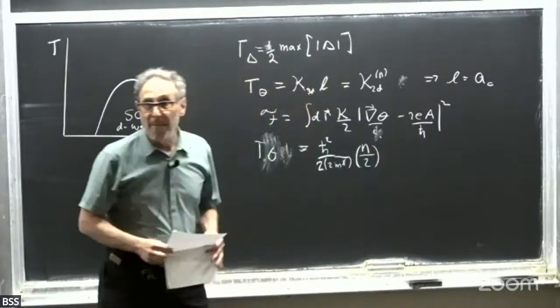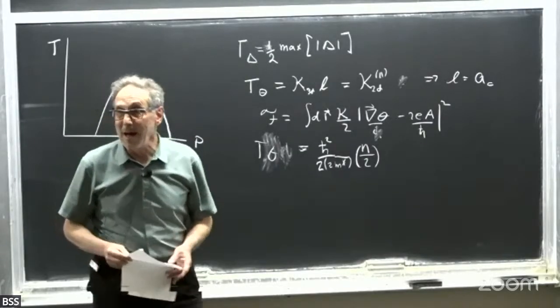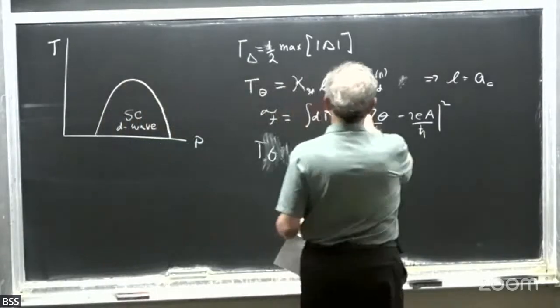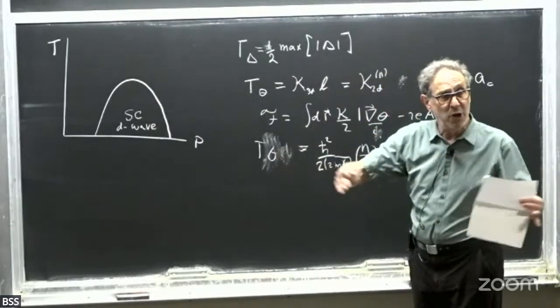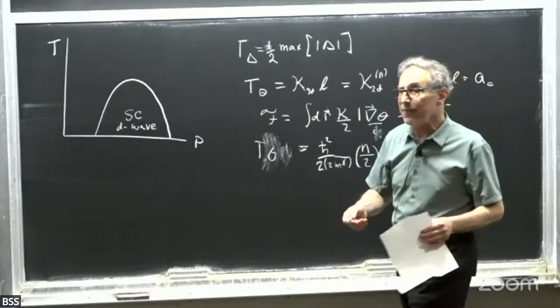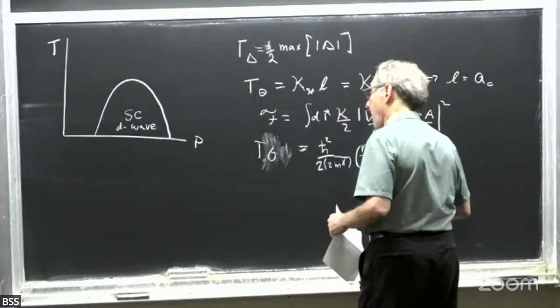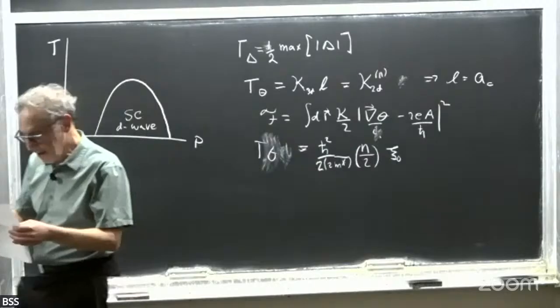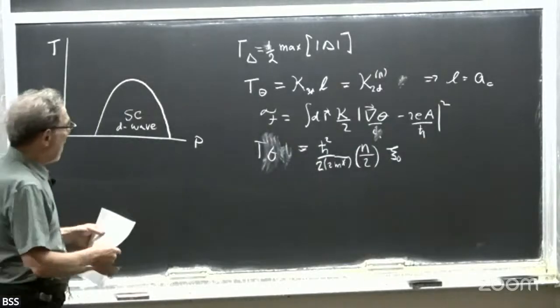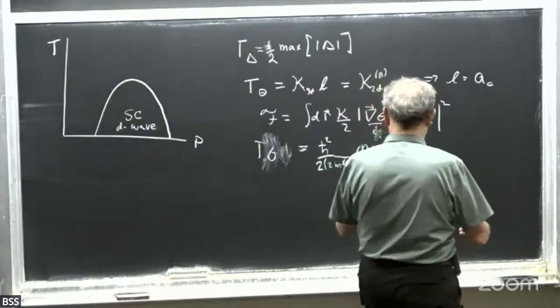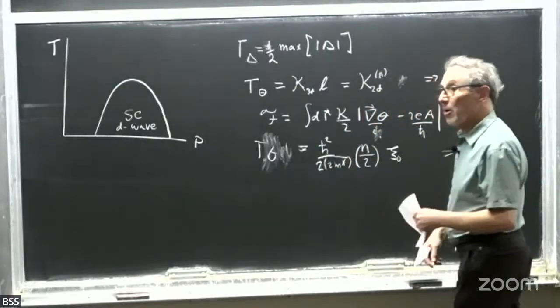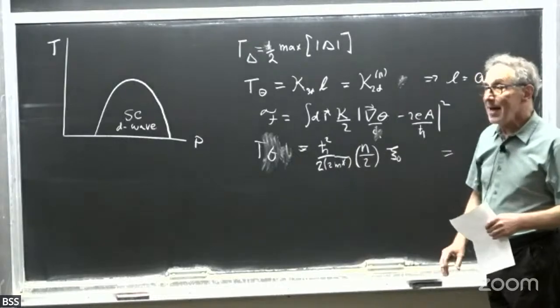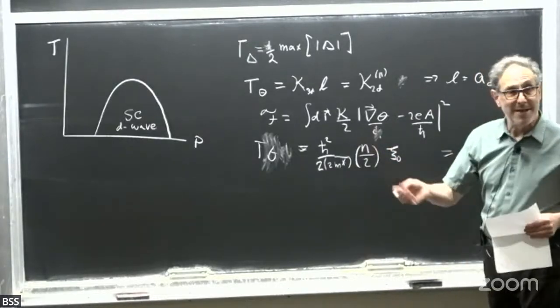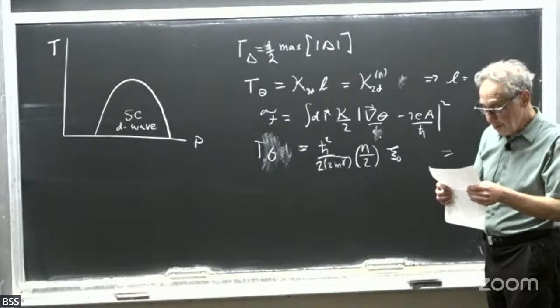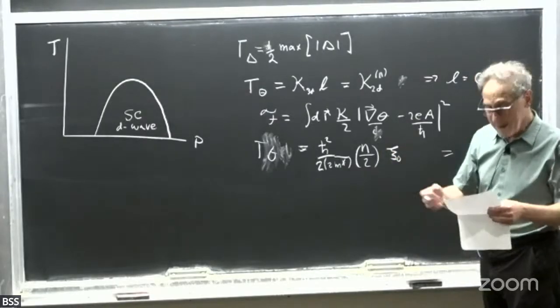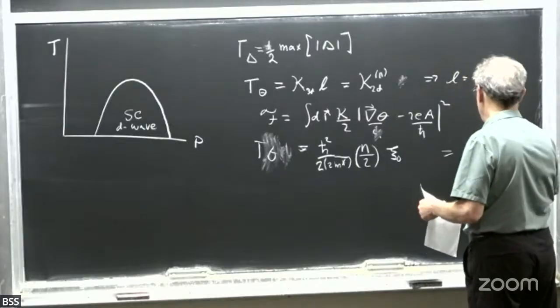This is from the 3-dimensional density. And then the length scale is the shortest allowed length scale for phase fluctuations, which should be something like the superconducting coherence length. So if I compute what T theta is for, say, lead or some typical metal with a mass that's on the order of the electron mass, a density that's maybe 10 to the 22nd per centimeter cubed, a coherence length that's maybe 1,000 angstroms, this comes out to be 10 to the 5th Kelvin.